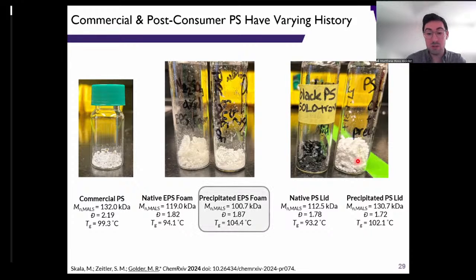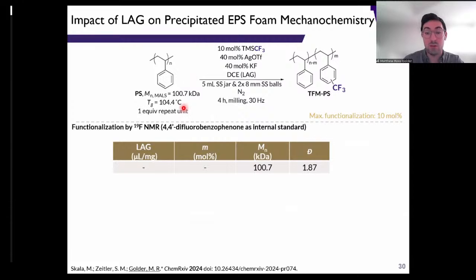So I'm going to show you just an emblematic example of what we did from here to start putting these post-consumer materials into the ball mill, working off of this precipitated foam. So we're working with this high molar mass material where we've gone through and we've removed as much of the additives and plasticizers as we can. So we could take this roughly 100 kilodalton polymer, we could subject it to the same conditions in the ball mill for trifluoromethylation. Again, the math is worked out here such that our max functionalization is 10%. So we're using 10 mol% of the trifluoromethylating agent, so we can get a maximum of 10 mol% tagging on our backbone here.